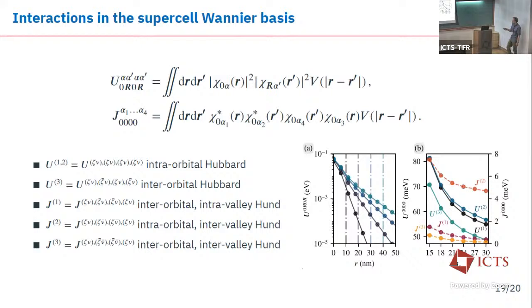All of those are much bigger than anything else, because here you have a second Y scale for the Hund-type interactions. The Hubbard interactions come out at roughly 80 meV at the largest, and the Hund interactions, all those intra-orbital or inter-orbital, inter-valley, or both, Hund couplings, come out at maximum, say, 8 meV, so a factor of 10 smaller than all Hubbard interactions. And what we also see is that with screening distance for a certain size of the supercell, we can reproduce the exponential tail of the long-range part of the Coulomb interaction that we expect for all lengths that are greater than the screening distance.